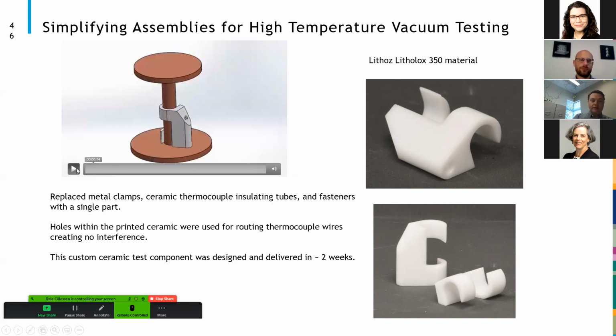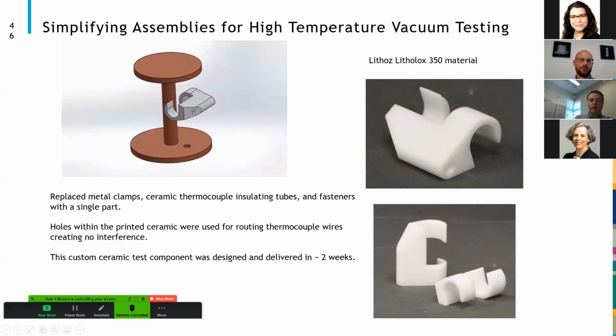The innovative design of this component was to allow assembly onto an existing subassembly to do a thermal measurement over the existing part. Holes within the printed ceramic were complete. This was different from the assembly that would require very delicate components. This was a very nice component, was delivered to the customer, and very successful in testing.